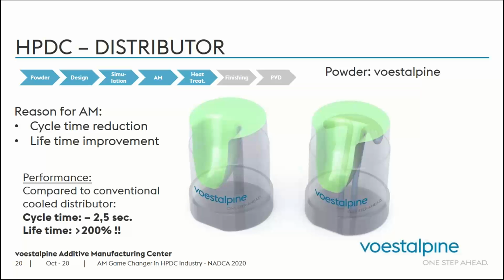In this case, the original cycle time was 53 seconds. We were able to drop it to 50.5 seconds, so 2.5 seconds per shot. That was the saving that we were able to realize on this distributor. And from our group, we provided the powder, we did the design, simulation, the building, and the heat treatment as well.